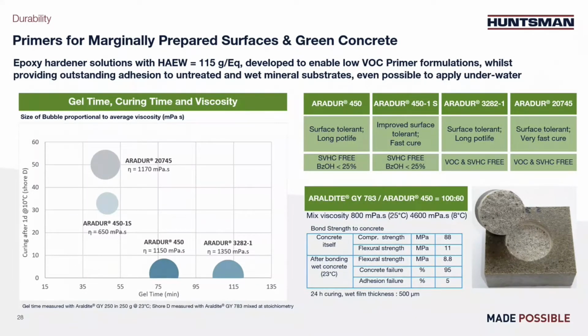So, durability. No surprise that primer comes first. So I'm going to speak about primer a bit. Generally, primer is here to reinforce the surface of a concrete and also to ensure the better adhesion of the next layer. So in this part, we focus on primer for marginally or freshly prepared surface with no need for surface pretreatment. This range of products is designed to provide an outstanding adhesion and a good reinforcement of the concrete.